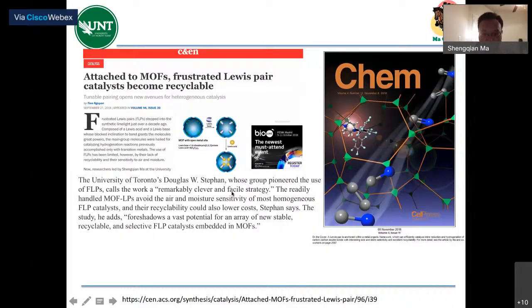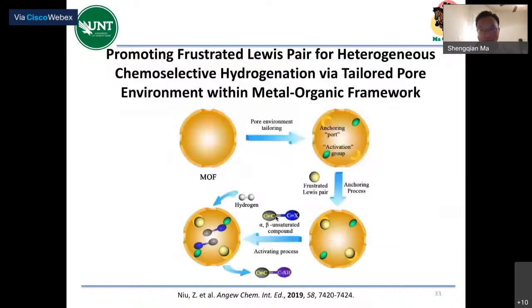What he said is, it's enormous. So we're very happy, and we demonstrate proof of concept. We can use the MOF to stabilize and to encapsulate the FLP, and to demonstrate some interesting catalysis which is not observed for homogeneous, like steric selective catalysis, and also size selective. Can we do something more using the MOF environment, the pore environment, because we know the MOF pore environment can be tailored. And can we do some more selective catalysis, like chemoselective, regioselective, and of course asymmetric catalysis? For FLP, asymmetric is easy. But for chemoselective, for FLP, currently it's very difficult to achieve in homogeneous system.